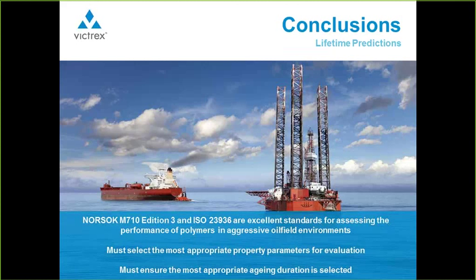It's important, as I hope I've demonstrated, that the aging period needs to be long enough to ensure that any possible degradation mechanisms are observed, and it may be necessary to use other means such as residual viscosity or GPC to increase the assurance for the customer on this.